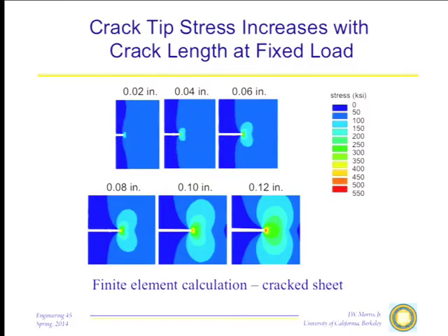So in this case, I would do the same calculation, where we took the crack, fixed the load, I forgot what it was. Anyway, we fixed the load, and I just grew the crack. You see as the crack gets longer, the stress builds up and up and up until finally it becomes very, very big out here. So if you have a crack in the material, you can load that crack up to the point that it just goes, either by increasing the load on it, and if the crack is sharp, that load at the crack tip is going to be huge, or you can increase the crack tip load by extending the crack, letting it grow until the load becomes so big that it breaks the material.